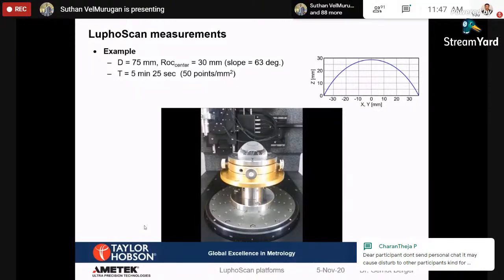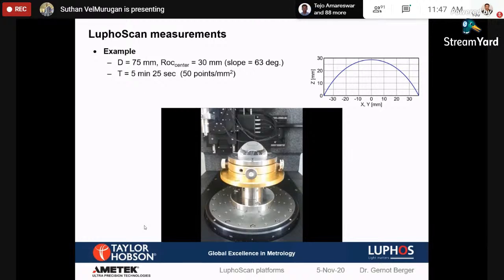So it is a single point, and it moved only one side, and during the rotation of the spindle, it covered the 360 degrees. It is like a spiral scan, so it collected the data for the entire 3D surface. This is approximately a slope of about 63 degrees. Still, we are able to measure the entire surface, but this may be a limitation in the contact profiler. We may have to tilt the sample, or tilt the traverse unit. Here we need not tilt anything because we have a tilt option in the probe itself, so the probe can tilt according to the slope of the part and collect the data.